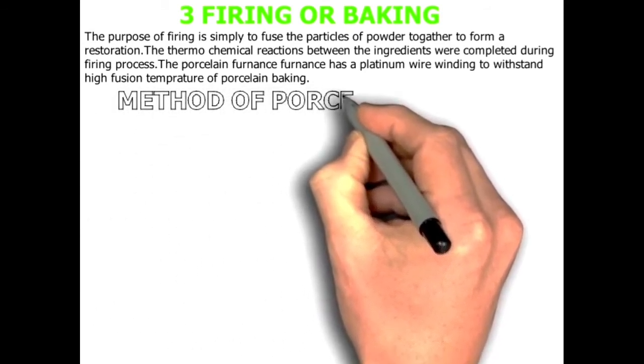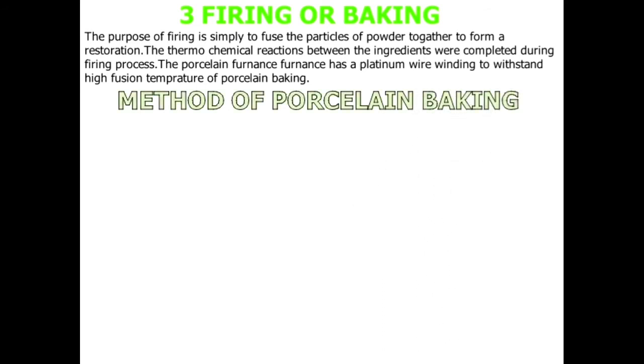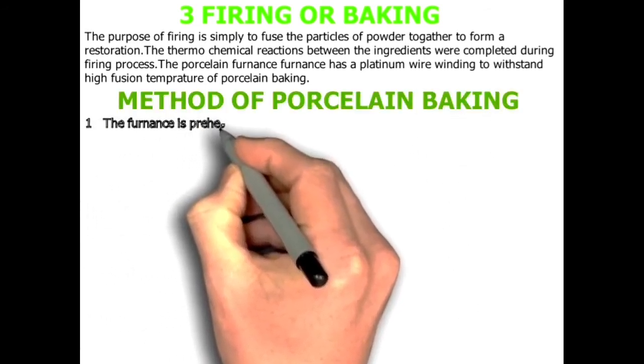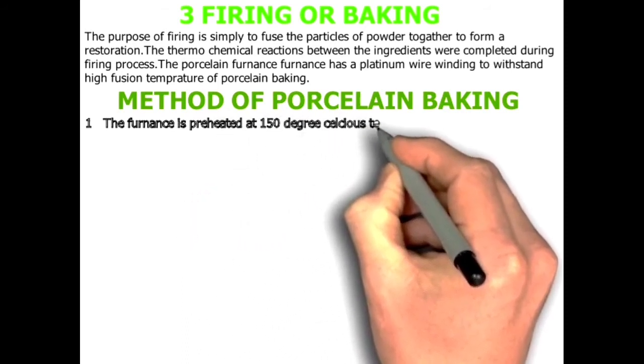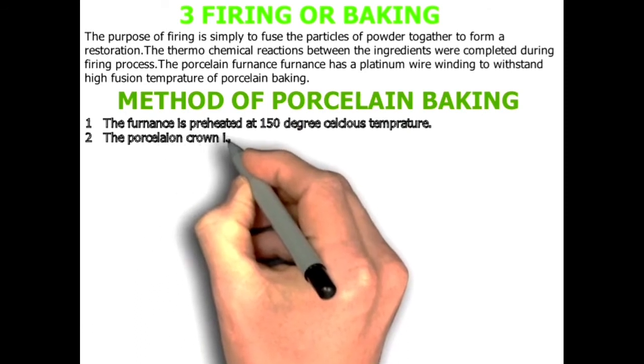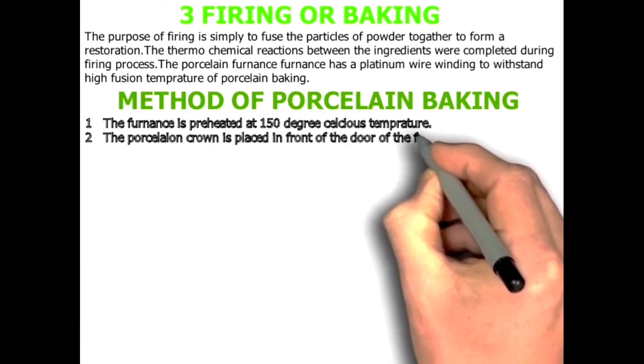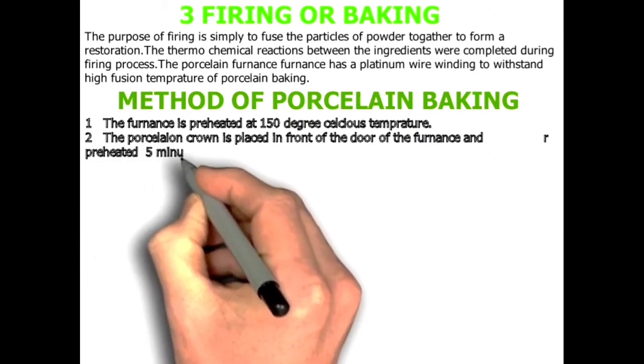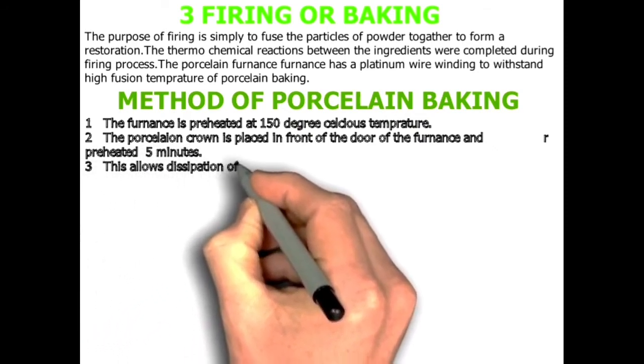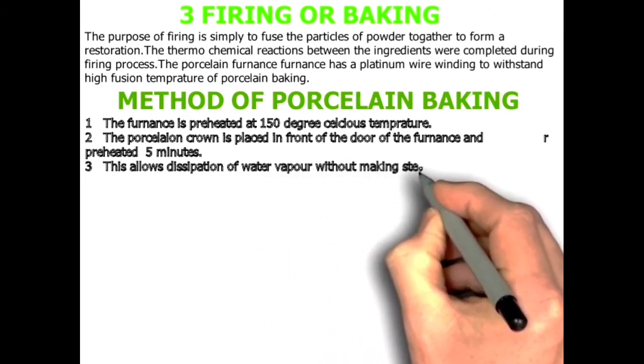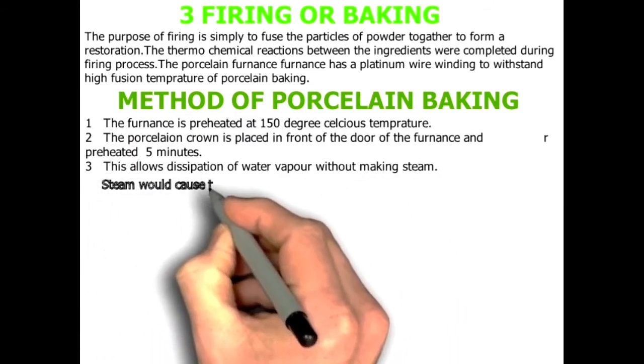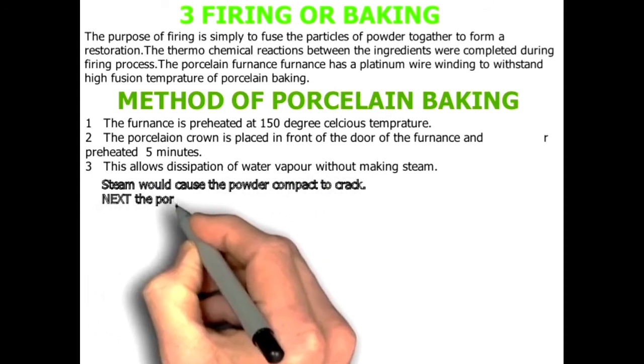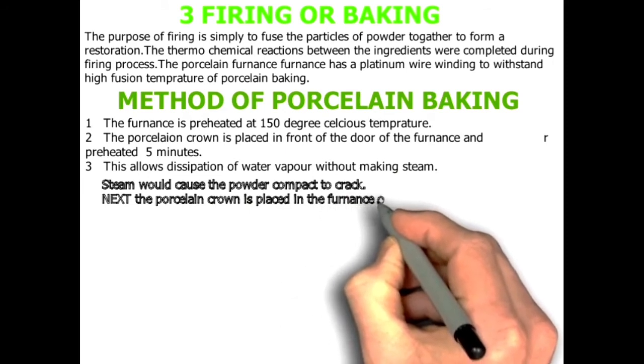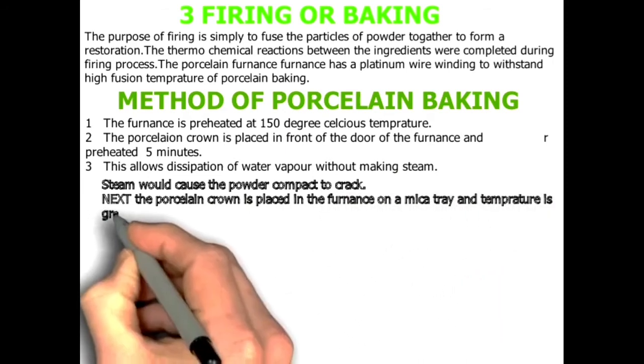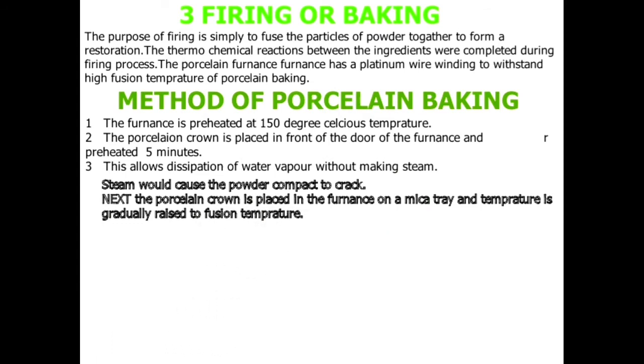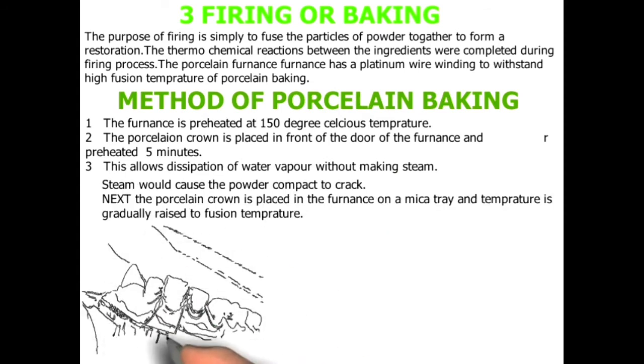Method of porcelain baking. First, the furnace is preheated at 150 degrees Celsius. Point number 2, the porcelain crown is placed in front of the door of the furnace and preheated for 5 minutes. Point number 3. This allows dissipation of water vapors without making steam. Steam would cause the powder compact to crack. Next, the porcelain crown is placed in the furnace on a mica tray and the temperature is gradually raised to fusion temperature.